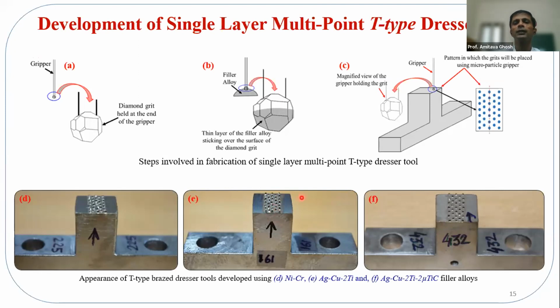So for this placing of the grits, we need to develop certain technology through which you can plant these abrasive grits on the filler alloy. So basically we paint the top surface, the active area, and then with the help of a state-of-the-art technology, which is also developed and patented by us, we just pick the particles and drop them, and then create a typical array, and then we allow it to braze.